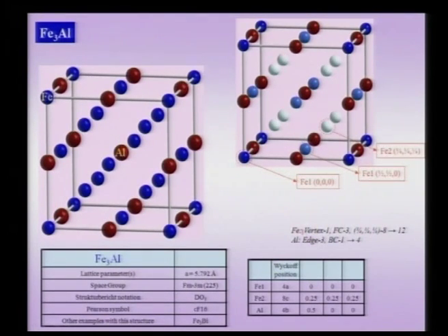You can see that all the 8 atoms in the vertices, 1, 2, 3, 4, all the 8 atoms together give us a contribution of 1 iron atom to this unit cell. So, vertex atoms give 1. There are 6 faces and there are iron atoms at these faces, and together they give a contribution of 3 iron atoms to this unit cell.